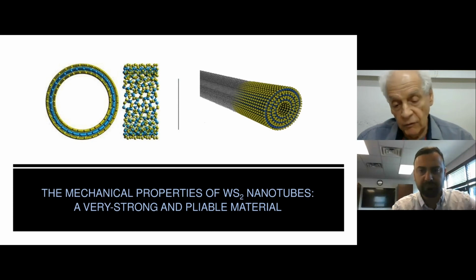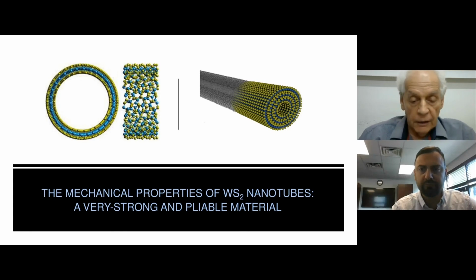Because if you take tungsten and sulfur, the sulfur is much more volatile than tungsten, and you remain with sulfur vacancies, and these sulfur vacancies induce negative charge on the surface of the nanoparticles. So in summary, these nanoparticles are negatively charged, and you see it very clearly in zeta potential measurement and in other measurements. Also, if you do electrochemical deposition or electrophoretic deposition, they will always be attracted to the positive electrode.